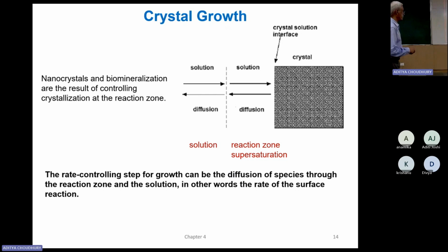The rate controlling step for growth can be the diffusion of the species through the reaction zone or the solution. In other words, the rate of this surface reaction. So what happens if you have a crystal and you just disturb it, so that the concentration becomes the same everywhere? Then you don't grow anything. That's why, whenever you grow a big crystal, every now and then they replenish. Say you are growing copper sulfate. After a few days, once a big crystal is formed, the concentration becomes very low. Then it started dissolving back. So you need to add more, to allow more nuclei and more small crystals to form, and that will contribute to the growth of the big crystal.